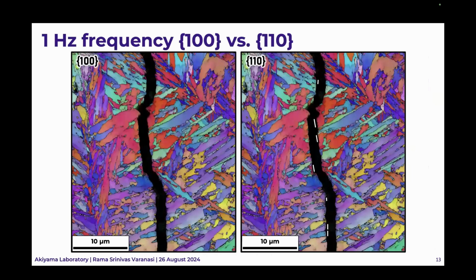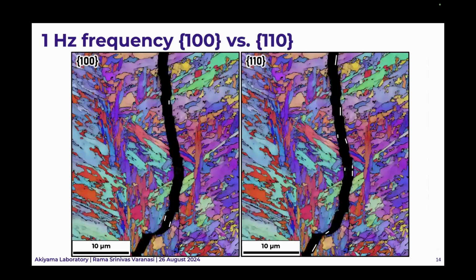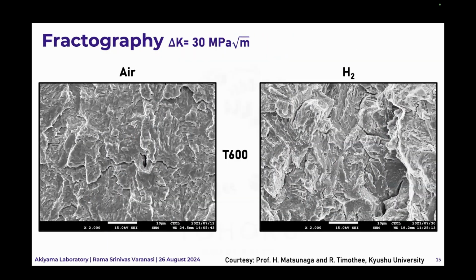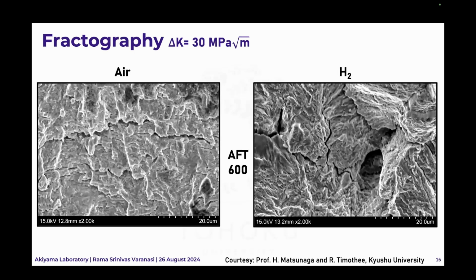And we also tried to look if there is any specific crystallographic mode. Occasionally we saw some 110, but there were many areas, for example here, where it was completely trans-lath growth. However, there was no specific crystallographic cleavage plane associated with this. We'll come back to it probably at the end. The fractography also shows the same story. This is for the T600, we see some intergranular features. However, in AFT materials, we have no intergranular cracking.